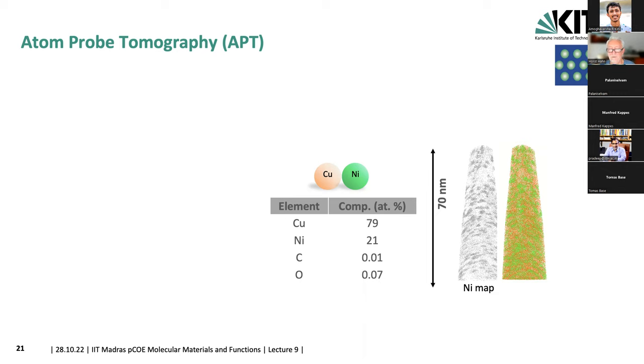So first of all, if you take one of these samples, what we were aiming for, or what we measured, was 79 to 21%. We have very little carbon, and also very interesting, we are very clean with oxygen, considering that the clusters are formed in an inert gas atmosphere, and then they travel in ultra-high vacuum for 4 meters before they are deposited. So we have a very good control of the composition here.